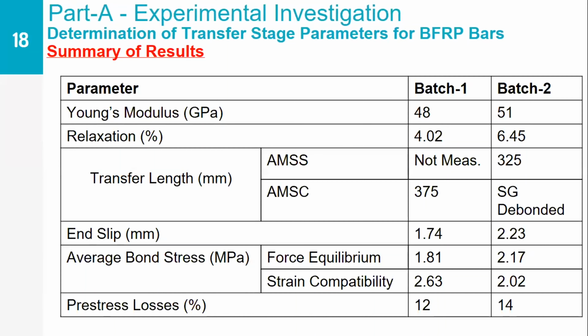So this is the summary of the results that were obtained from these tests. So we could get relaxation of between 4 to 6% for the two batches. The Young's modulus was between 48 and 51. However, for the first batch of specimens, the strain gauges were not used for measuring the transfer length. So we have only used the concrete strain gauges. So that gave a transfer length of 375 millimeters for a BFRP bar of 8 millimeter diameter.